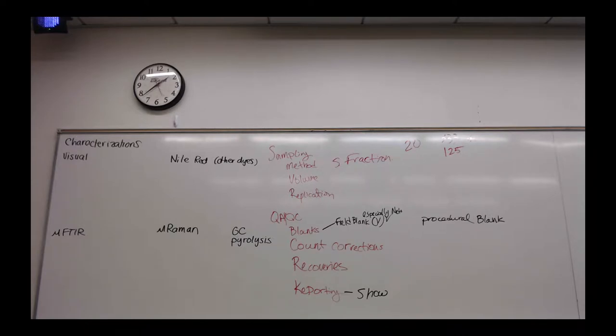So first we did a visual quantification with a stereoscope or dissecting scope, and we used rules on morphology, shape, and color that were similar to what Cara presented today when you guys were all looking through your dissection scopes. And then we stained with Nile Red and we used a crime light similar to what you guys were doing in the lab today with the stereoscopes and the orange goggles.